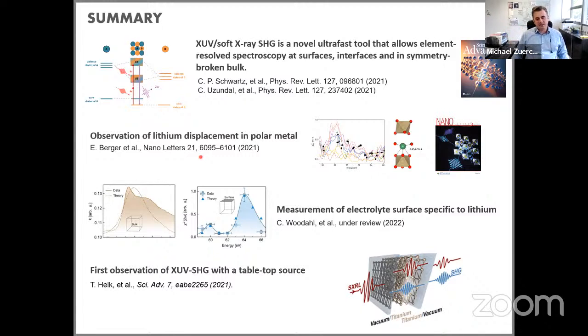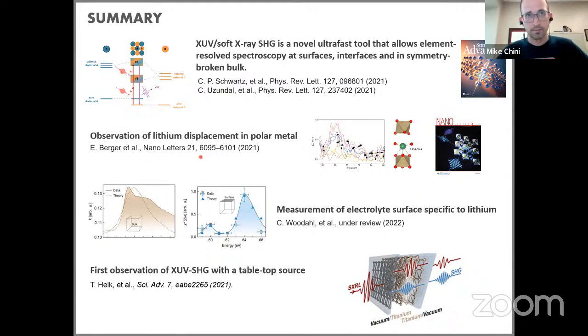And that's typically also, across these experiments I showed, always been the case. If we study a surface or an interface, we have to hit it actually quite hard. We have to increase the power of the FEL, go very close to the damage threshold, whereas if we are measuring bulk anisotropies, we can be a little bit more relaxed because we just get many more photons from the emission events. I see. So I would say for the lithium osmate, for example, this was a large area sample.